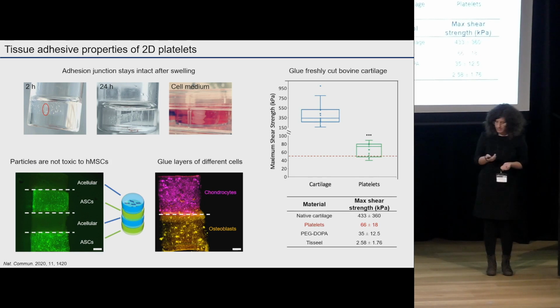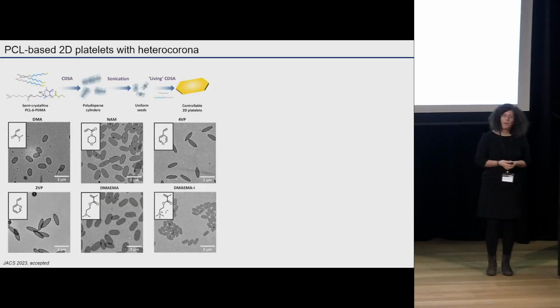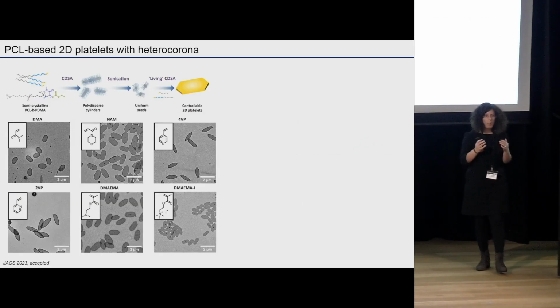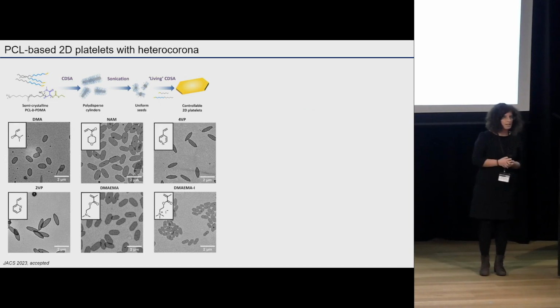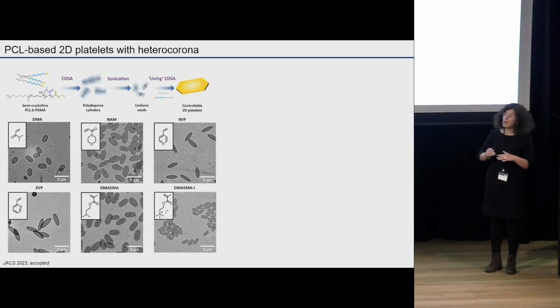So in the last few slides, as promised, what I want to tell you about is what control we have on the surface chemistry of the nanoparticles and what we can achieve by controlling the surface chemistry. And this is very recent work that had just been accepted last week. In this case, what we are manipulating is the hydrophilic bit of the molecule, so the part that stays outside. And you can see that by changing the chemistry, we're changing the shape of the nanoparticles.